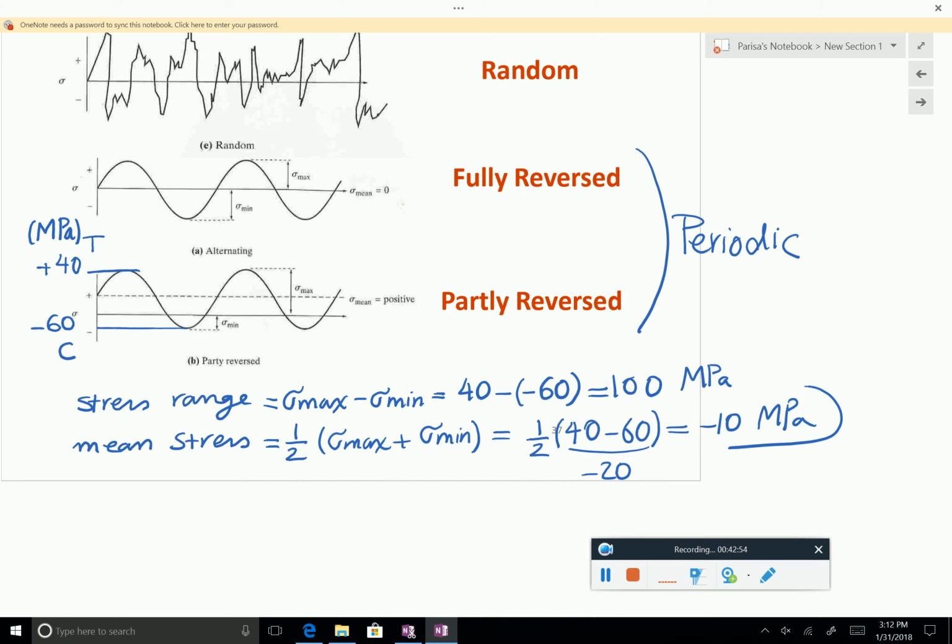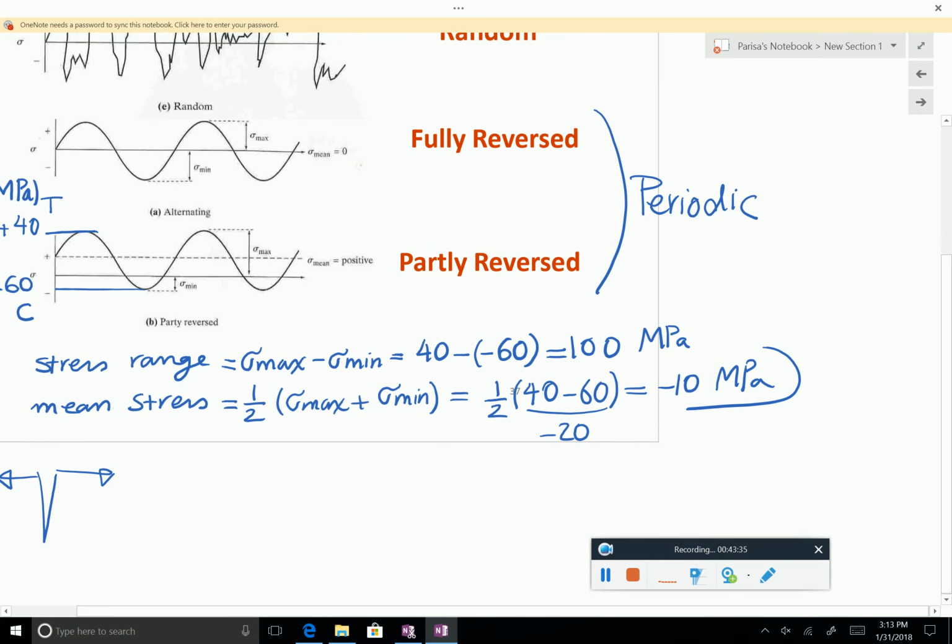Remember, what we don't like is tension. In fatigue or generally in brittle fracture, what makes crack propagation is when you have tensile force which wants to tear apart a crack. So if you have a crack here, what you don't like is to have the force which pulls it apart. If it is compressed, it is actually good because it's closing the crack, so you don't have issues. You'll see later that we try to use methods to have more negative stresses in the material.